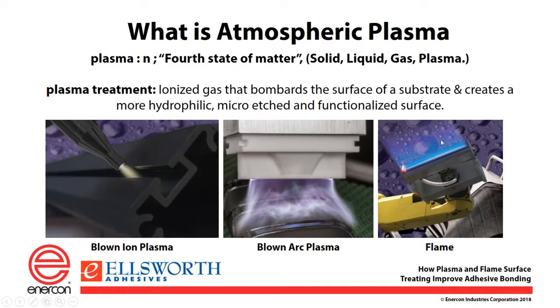And then, of course, flame. There's some advantages to flame over the blown ion in that you don't have to be quite as close to the surface to get a good treatment. Some parts that have more 3D type applications to them, you might want to use a flame because you're going to have different distances. When you're dealing with a blown ion type application, you need to be concerned about the distance that you are from the substrate at all times. Flame is a little more flexible in that, but of course, there are other advantages and disadvantages to both, but we can help you pick which one would be the right application.